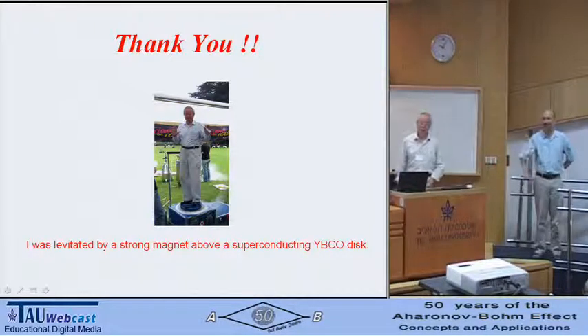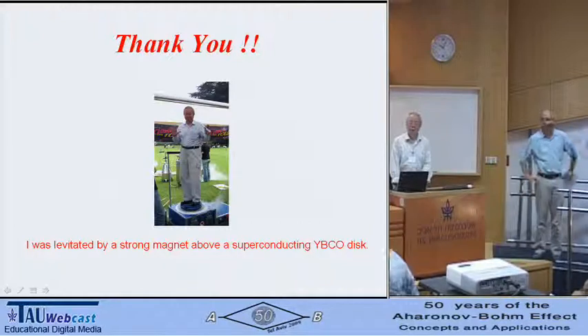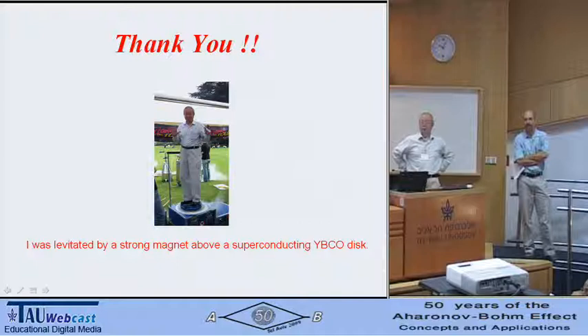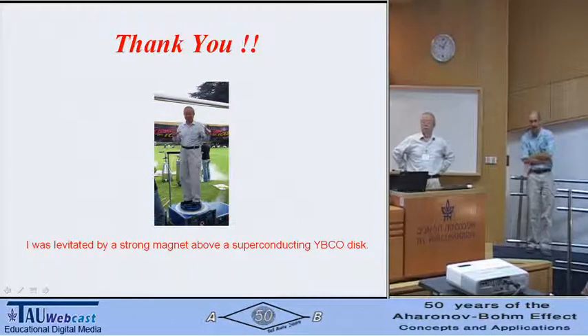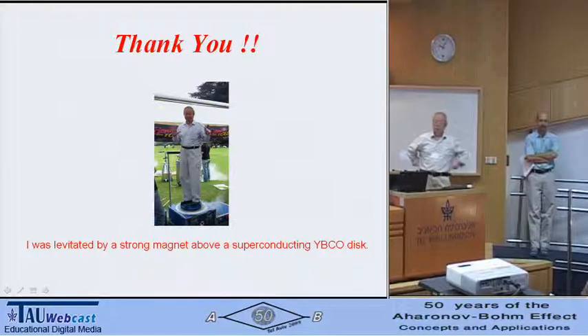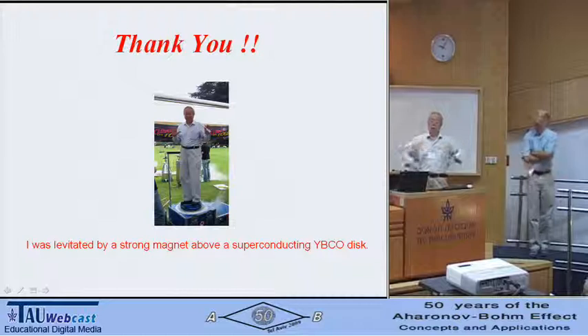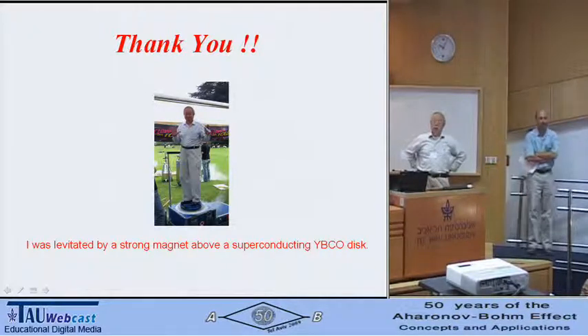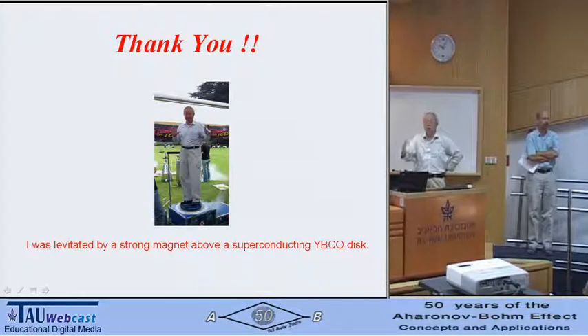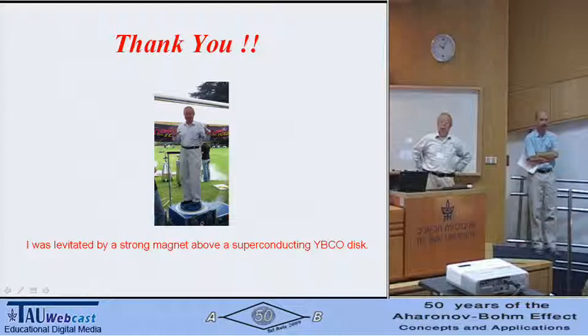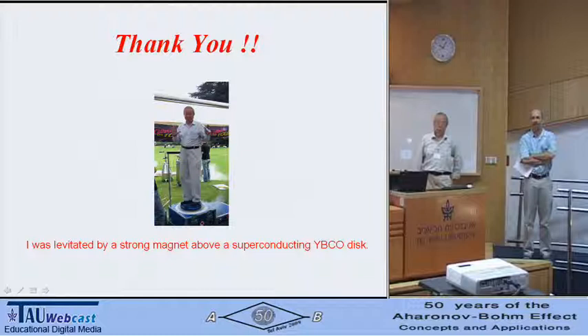Okay, so that's it. Thank you. You didn't say anything about the magnetic state above the superconducting transition. Are these antiferromagnets? Yeah, broadly speaking, it is antiferromagnet. But this material has a collinear magnetic structure, like this. Right. So the antiferromagnetism persists below the transition temperature. And you know that it's doping dependent. And the samples are big enough that you have neutron diffraction data on them. Yeah, I've been going through the literature, lots of data. Okay, the neutron scattering and other measurements. Thank you.